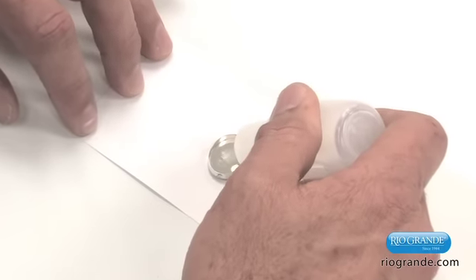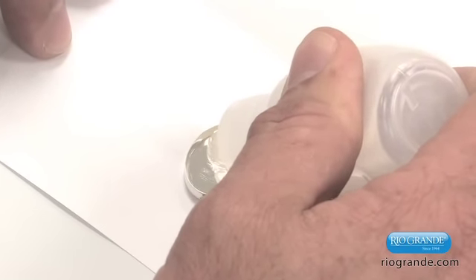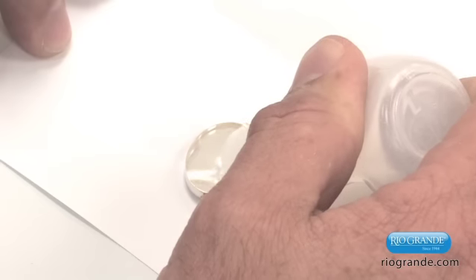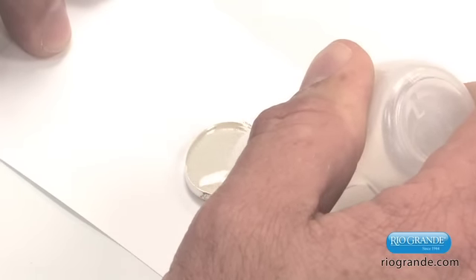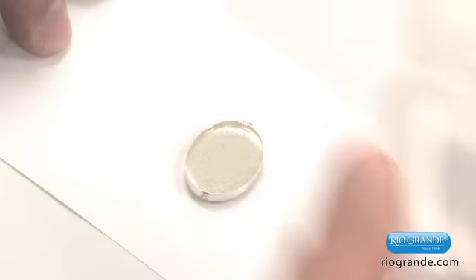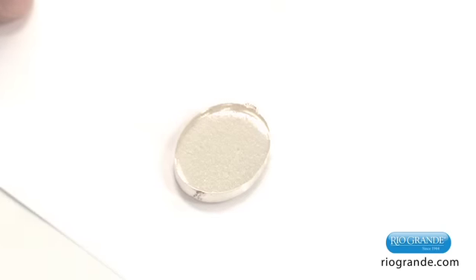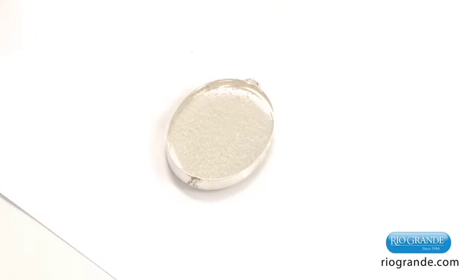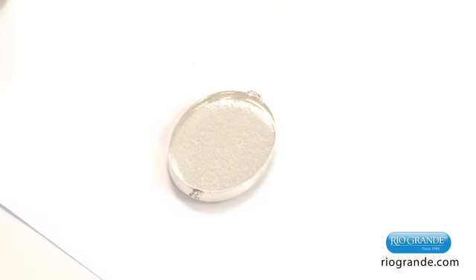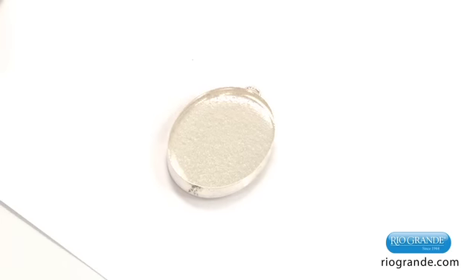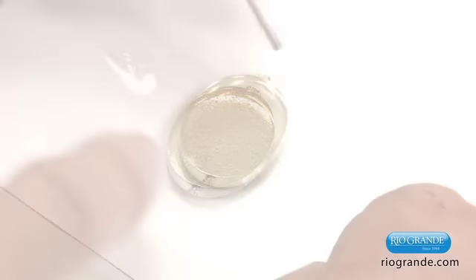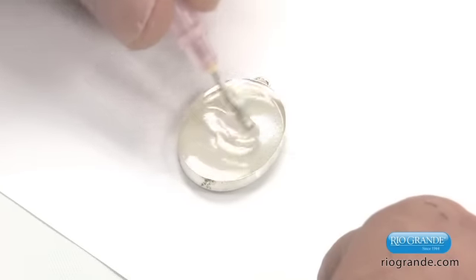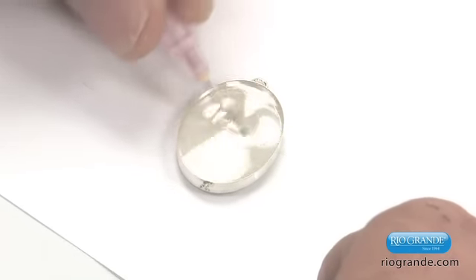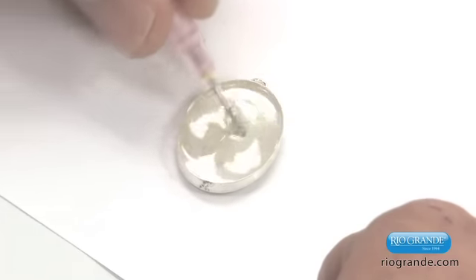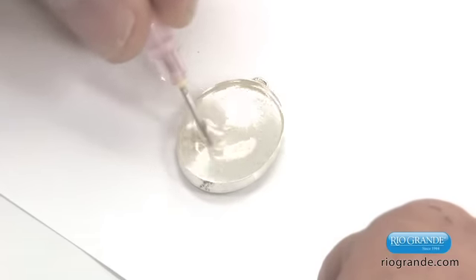Okay, I'm going to be demonstrating air bubble problems, and I'm going to be using a gross opening on the needle tip applicator without a needle to make this quick. Okay, it's obvious from looking at this piece I have a tremendous amount of air trapped in this mixture. That came from over-aggressive mixing, and if you see these types of air bubbles, it came from that. Now the way to get these air bubbles out is simply to either let this piece sit. Over time, the air bubbles will migrate up to the surface, they will pop, and the resin will re-level itself. You can also take the needle tip and simply agitate the resin to bring those air bubbles up to the surface to allow them to pop and to accelerate that natural process.